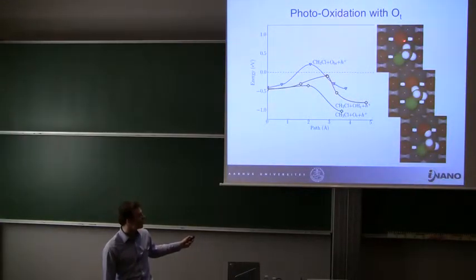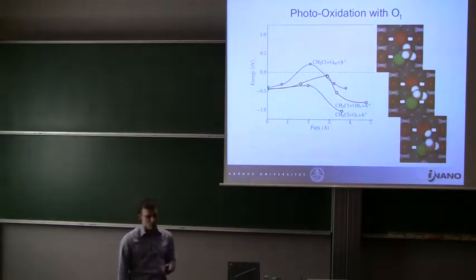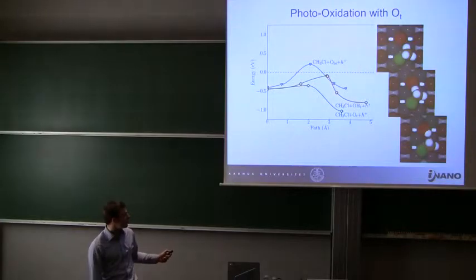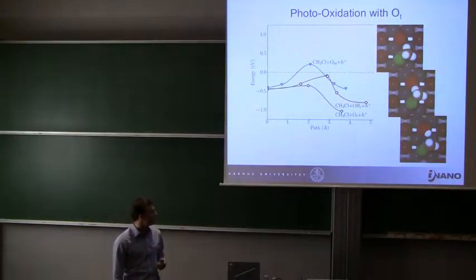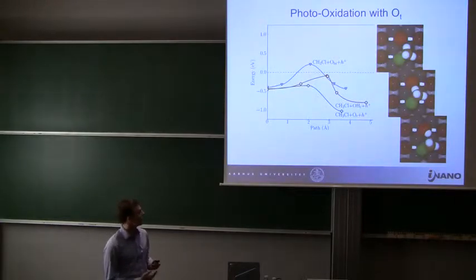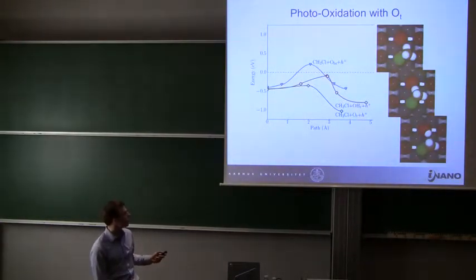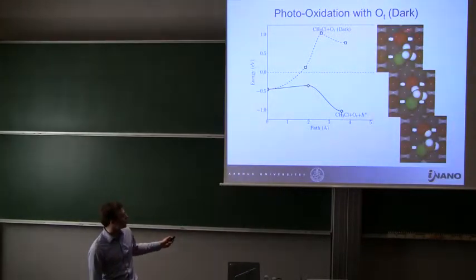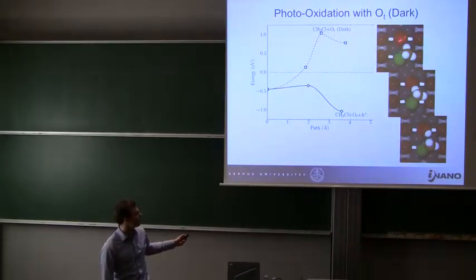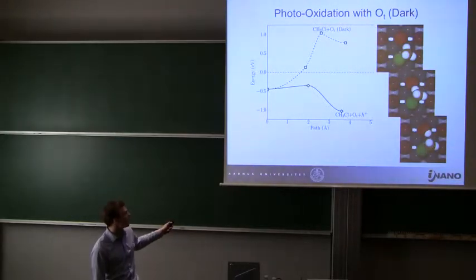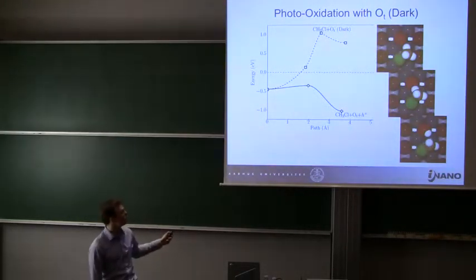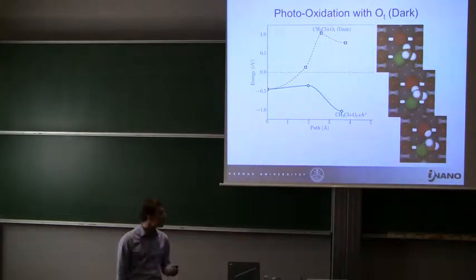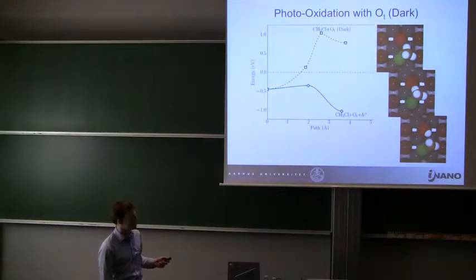And then finally, having terminal oxygen, which is the most reactive of these species, we see that the reaction goes very easily. But of course, these are all with the hole present. So what influences the reaction from the hole? Now trying to do it without the hole, and again with the most reactive species, the terminal oxygen as a proton acceptor, now we see without the hole everything is very unfavorable, both the transition and the final state. So it seems that we have now two species that can catalyze this CH bond-breaking.